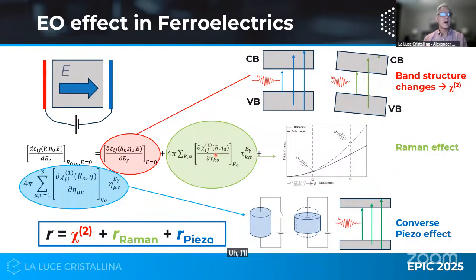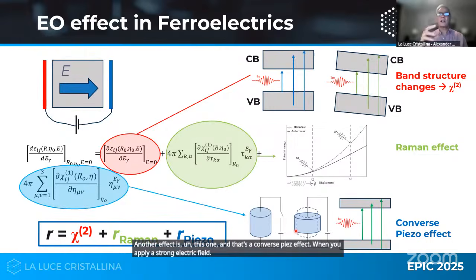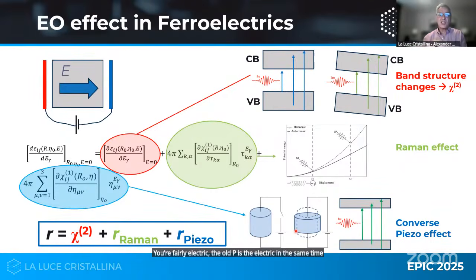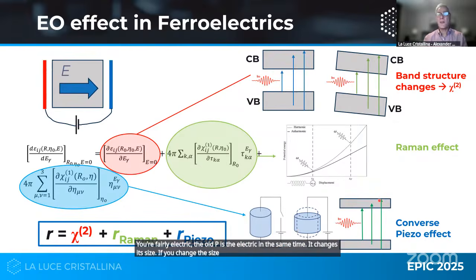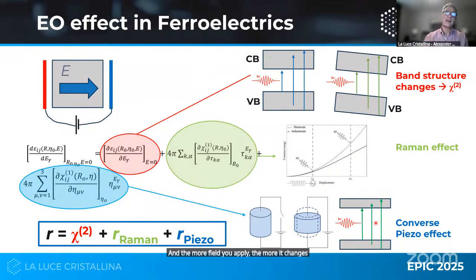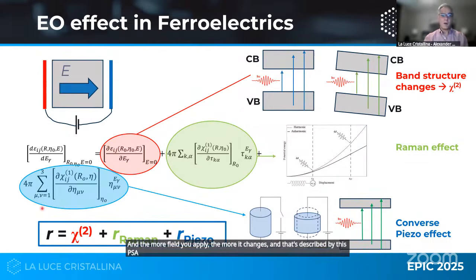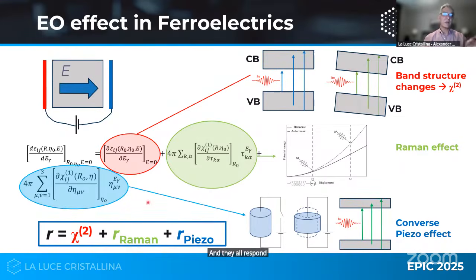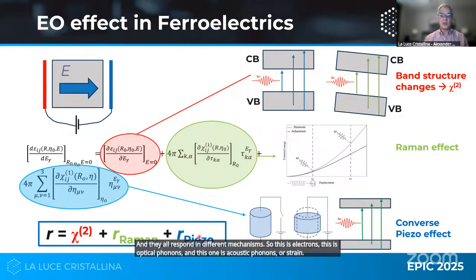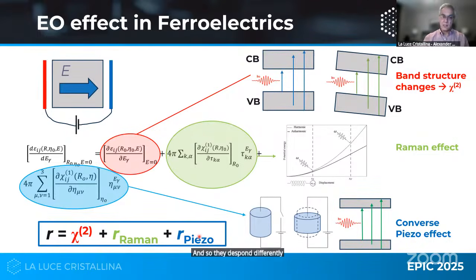Another effect is this one, and that's the converse piezo effect. When you apply strong electric field to your ferroelectric, which is also piezoelectric at the same time, it changes the size. If you change the size, the width of the bands changes, the band gap changes, and so all these transitions change, and so chi1 would change. And the more field you apply, the more it changes, and that's described by this piezo component. So for the purpose of our discussion, remember there are red, green, and blue components to the Pockels effect, and they all respond by different mechanisms. So this is electrons, this is optical phonons, and this one is acoustic phonons or strain. And so they respond differently to different stimuli.